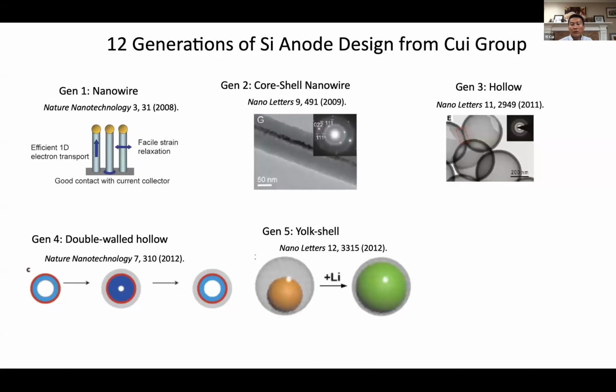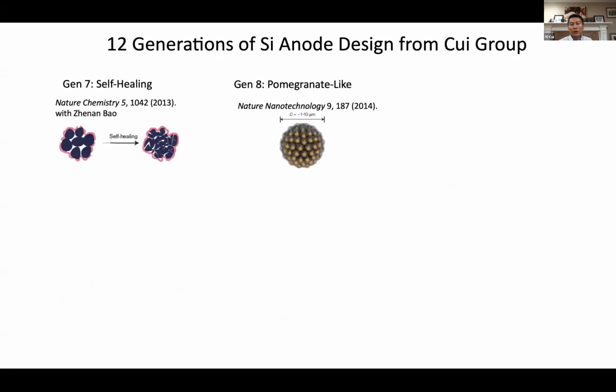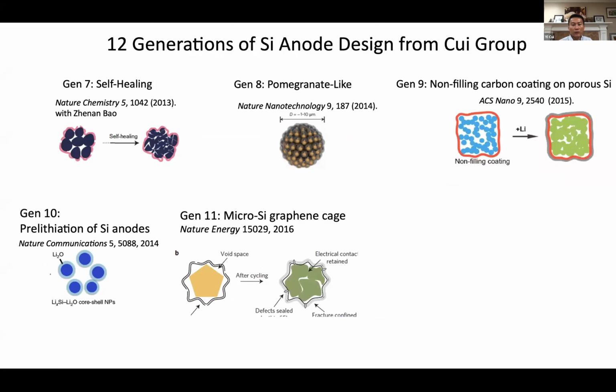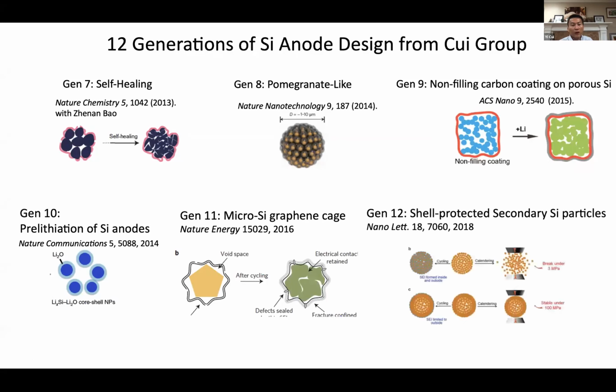And with time, we also go down to the low cost version, go down to the micron particle, even if they're breaking. Make sure they break inside a framework so they do not destroy the surrounding environment, still allowing you to build a stable interface until nowadays. I won't repeat everything. But I would say designing in nanoscale is so powerful, but this problem I mentioned earlier, the high surface area of a nanostructure reacting with electrolyte.